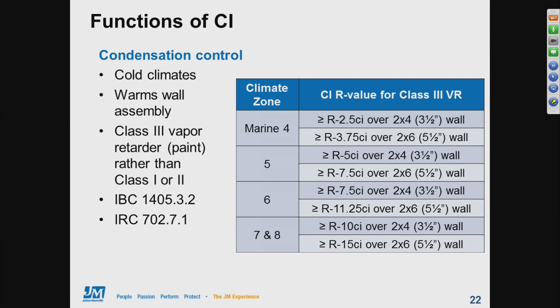An important point to note is that in some cases, especially in climate zone 6 and above, the CI R-value requirement for condensation control could actually be higher than what's required by the Energy Code. This is really a problem that the designer has to deal with, but it's something that shouldn't be ignored. The requirements listed in the table that we have on the slide are actually also present in both the International Building Code, which covers commercial construction, and the International Residential Code for homes.